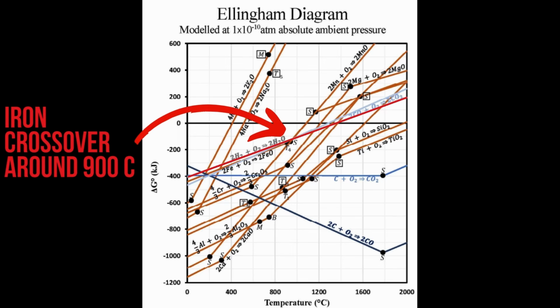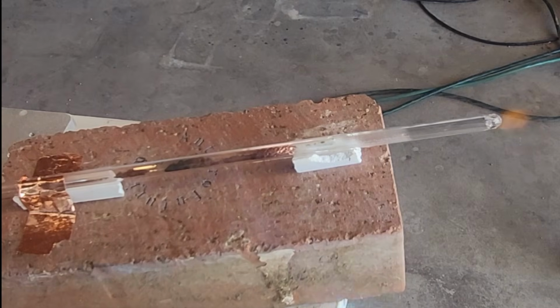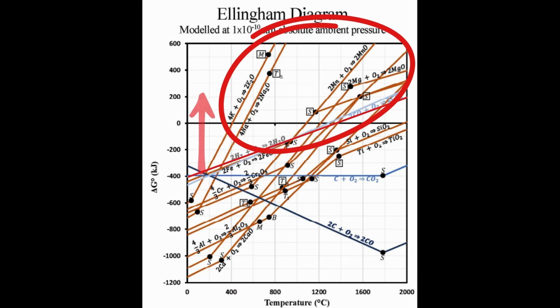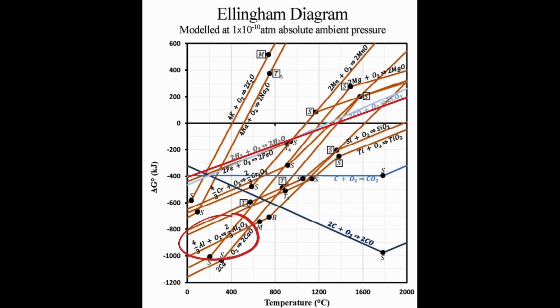And what this means is that hydrogen reduction should be able to yield all the iron in the regolith, not just the free iron in the case of the milling and mining method. So you get more bang per kilogram. But of course, as you can see by looking at the diagram, hydrogen is still limited in what it can reduce. And we want, well, pretty much all of the elements in regolith because they're all extremely useful. Aluminum for electrodes and reflective surfaces, and silicon for solar cells and other semiconductors, and titanium for structures, and chrome for corrosion resistance, just to name a few.